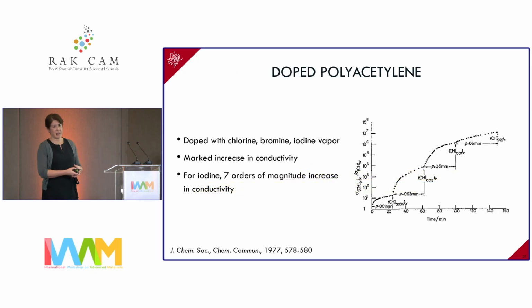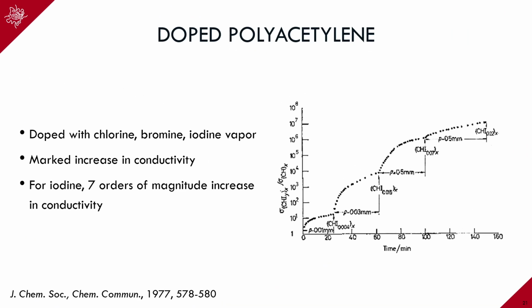So just looking at a little bit more detail about what they actually did, they made the polymer polyacetylene, and the really classical experiment that they performed was to dope polyacetylene with various halogens: chlorine, bromine, iodine. And you can see that with increasing dopant, you could obtain a huge increase in conductivity. In the case of iodine, they actually achieved a 7-order-of-magnitude increase in conductivity, which is where you're starting to match the conductivity of metals. So I just want to highlight this story in particular for the students in the audience. These kinds of accidents can really lead to major discoveries. So I hope you'll embrace the accidents that you might have in your lab as well.